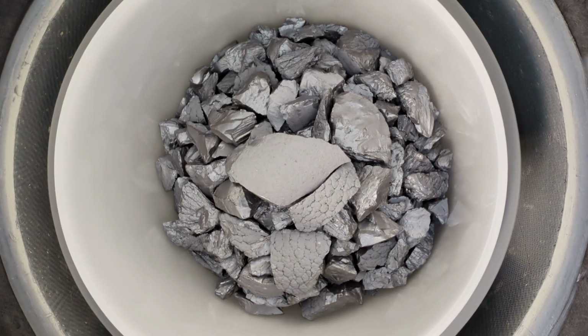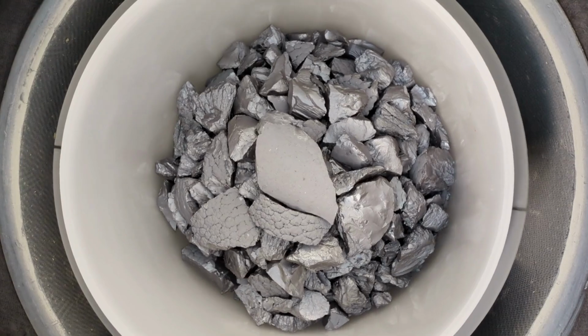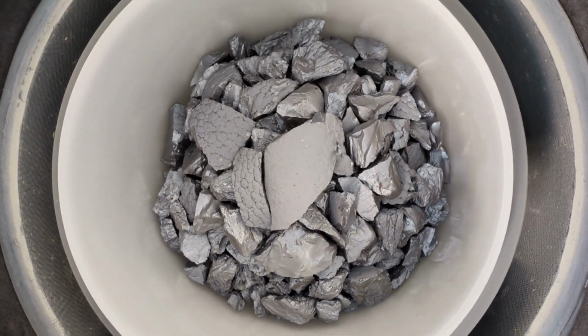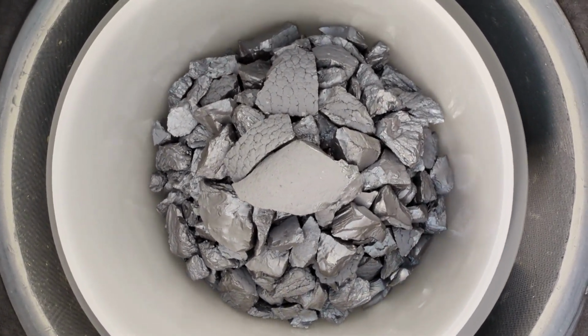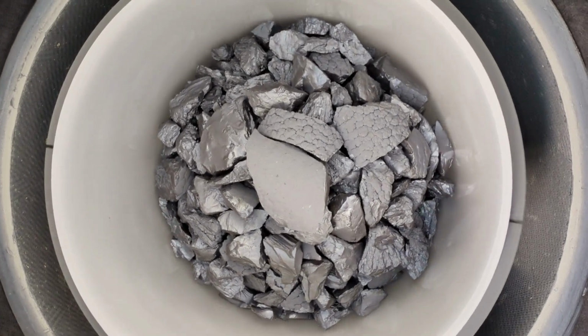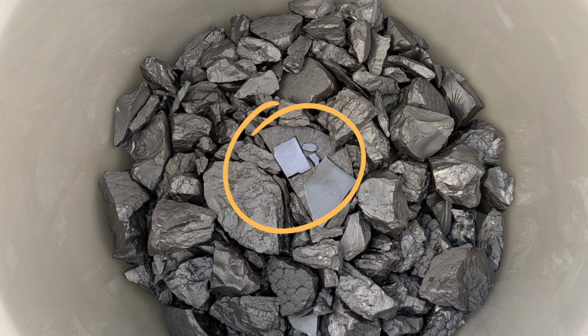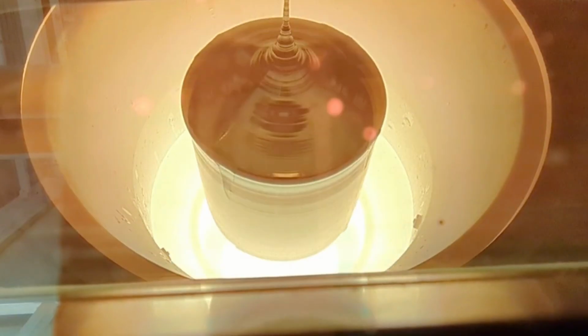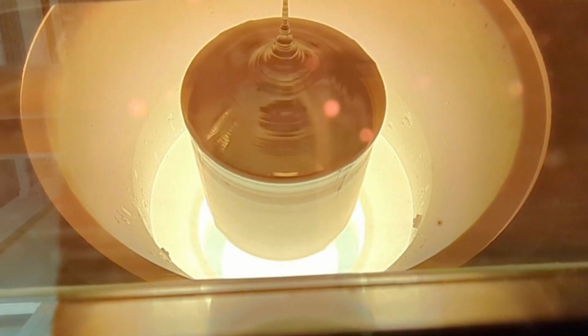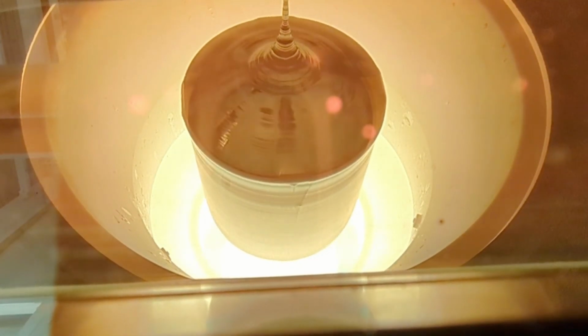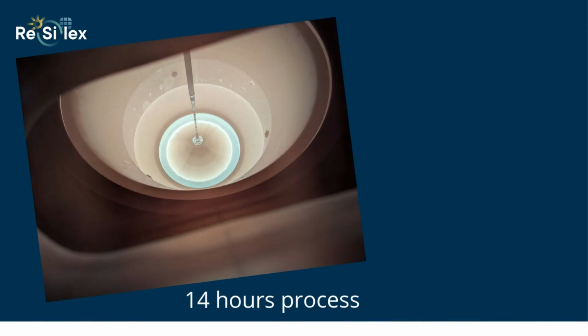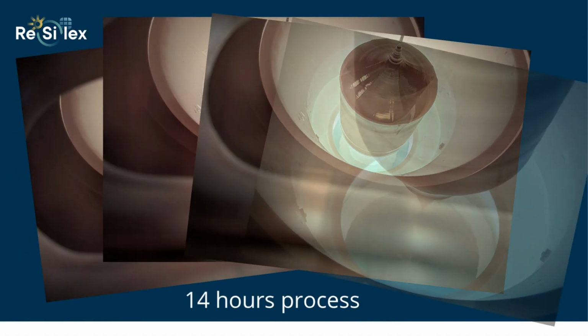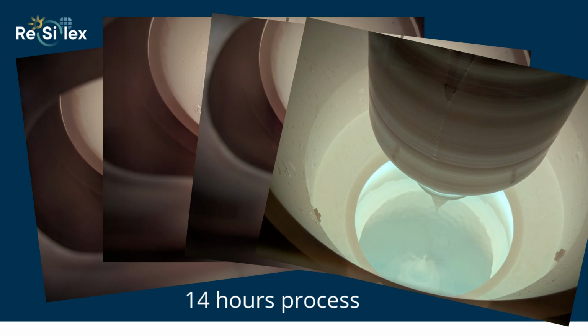Well, the pulling started with the load of the crucible, with the addition of 3.5 kg of the recycled silicon, followed by the electronic-grade silicon and finally the phosphorus dopants. A calculation was performed for each ingot to determine the exact amount of phosphorus to add, which would compensate for the high boron concentration present in the recycled feedstock.